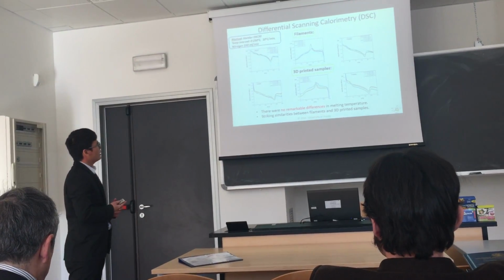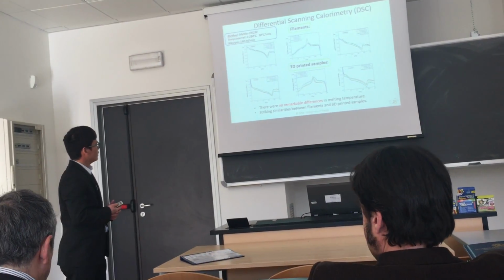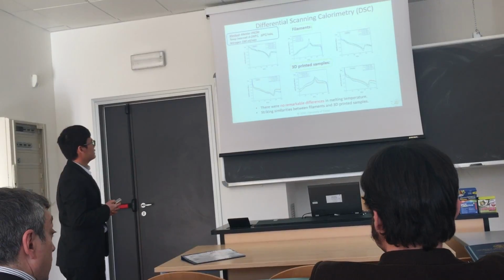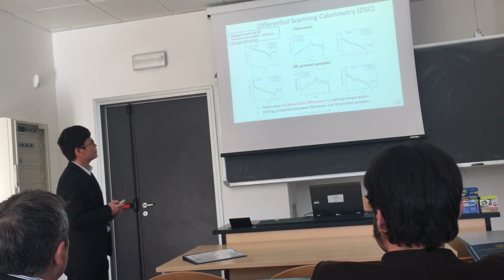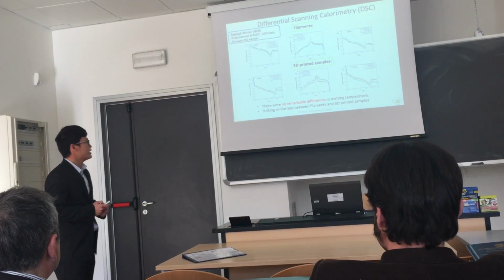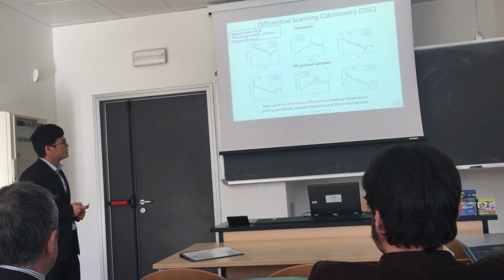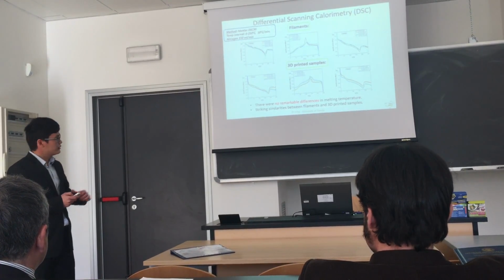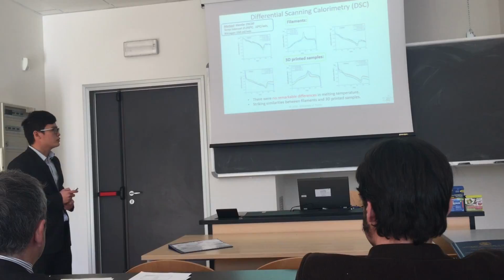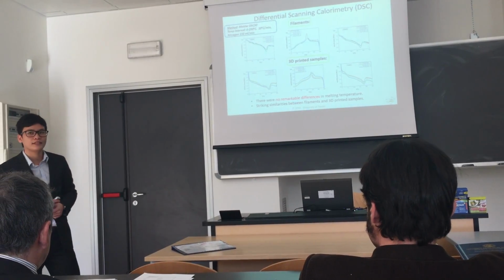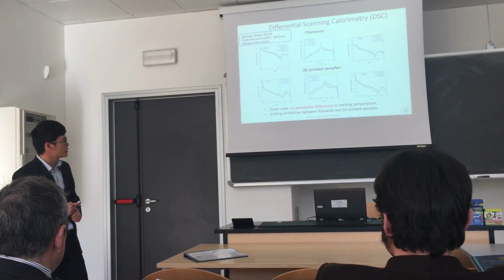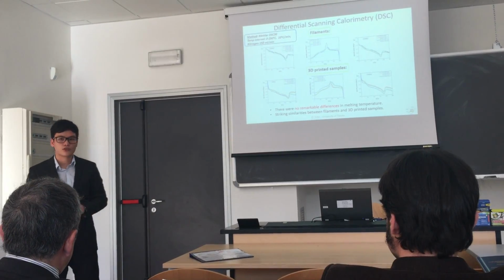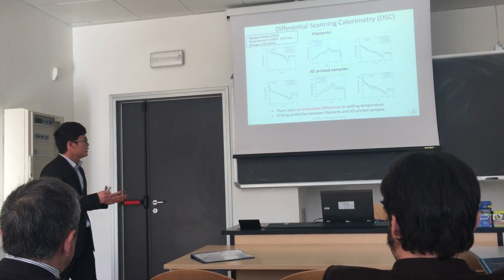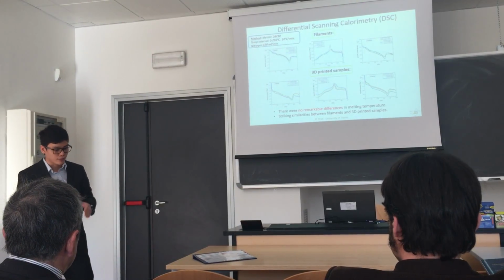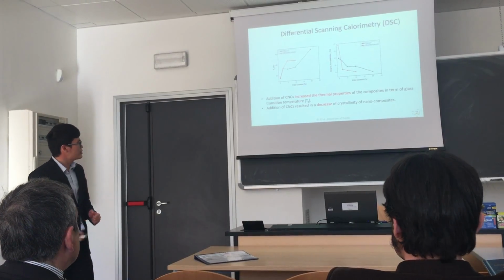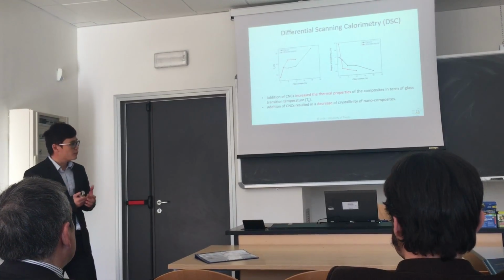For the DSC thermogram, we can see from the figures that in the comparison between the filament and the 3D printed sample, there was no remarkable difference in melting temperature. So this is a good point for the workability of the nanocomposites. There was also a striking similarity between the filament and the 3D printed sample. From the DSC results, we have some conclusions.